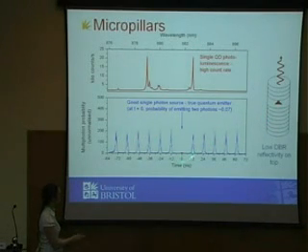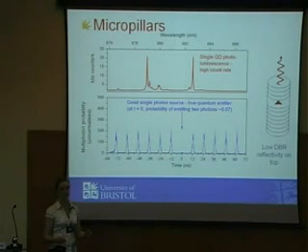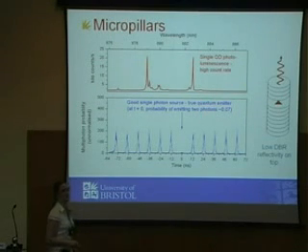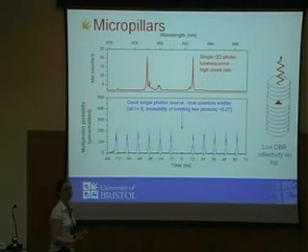But if you look at exactly time t equals 0 here, the probability that we have two photons arriving at the same time is 0, or in fact about 7%, because these devices aren't perfect. So you see that these quantum dots make very good single photon emitters. And if you have very good single photon emitters, there are many quantum computing proposals that we can implement.